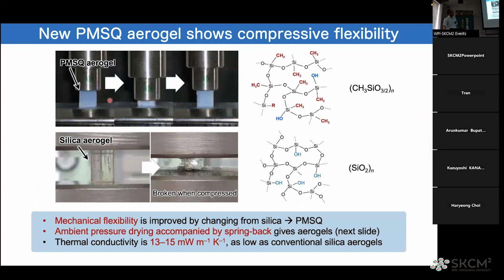This photograph shows the flexibility of our aerogel, called PMSQ aerogel, based on the chemical composition of the gel, polymethylsilsesquioxane. A little bit difficult, but we can say PMSQ. So the PMSQ is flexible like this. This is 80% compression and then it springs back to the original size without breaking, without any irreversible shrinkage. The network structure is like this. The methyl groups repel each other when compressed, so they show the spring-back behavior. Okay.